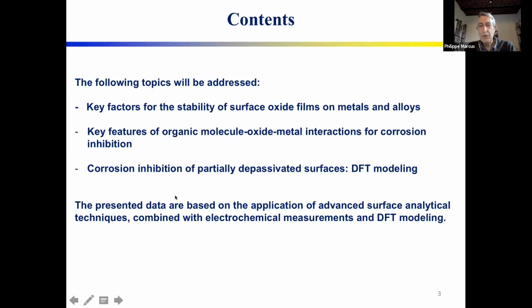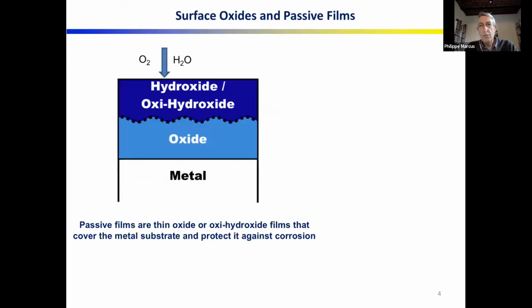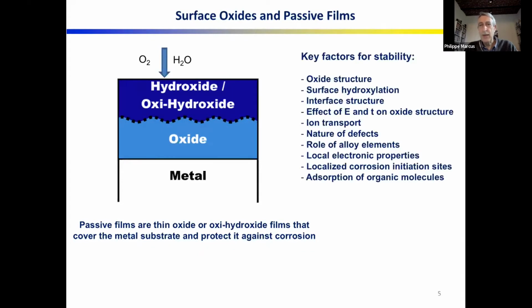All of the data presented today are based on the use of advanced surface analytical techniques, which are combined with electrochemical measurements and, in many cases, combined with DFT modeling and simulation. In a general way, surface oxides and passive films are very important because they cover the metal substrate, and in many cases they protect the material against corrosion. These films are extremely thin. They usually consist of an oxide and oxyhydroxide, and their stability is of primary importance for many metallic materials.